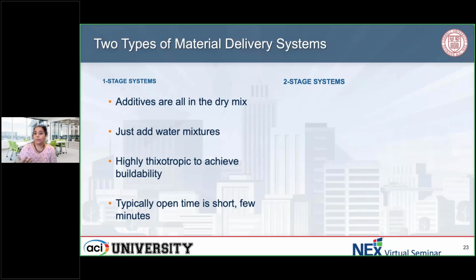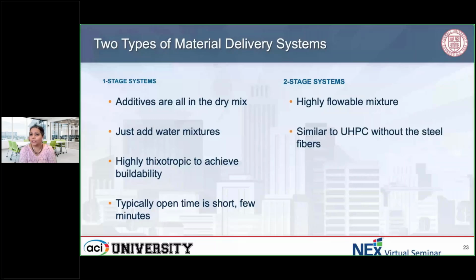Like I showed you with the Waterman mixer, we can mix a very flowable mixture. You can think of it similar to UHPC. It's very flowable, but doesn't have the steel fibers in it because our pump cannot pump steel fibers and really stiff fibers, and it also cannot pump, like I said, larger than 2 millimeter particle size.